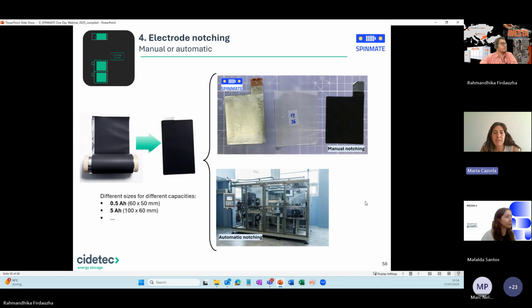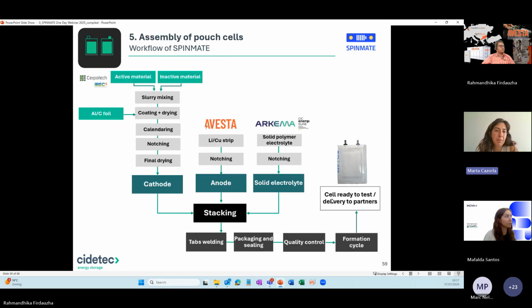So next, the next step is the notching or the cutting. Because when we get the coated electrode from our equipment, we have it in a roll. So then we need to cut it into sheets, different parts, and then we notch it with a certain geometry. Here it's very important to leave, as you see, a non-coated part that is actually the tabs in which the electrical connection between the electrodes, sorry, for a certain cell will be done. So here is an example of an anode, a solid electrolyte and a cathode that we have cut and then assembled in a SPINMATE cell. This is done manually, but it can also be automatized once the technology is at a more advanced step of the design. So once we have the electrodes, then we can go for the next step, which is the assembly.